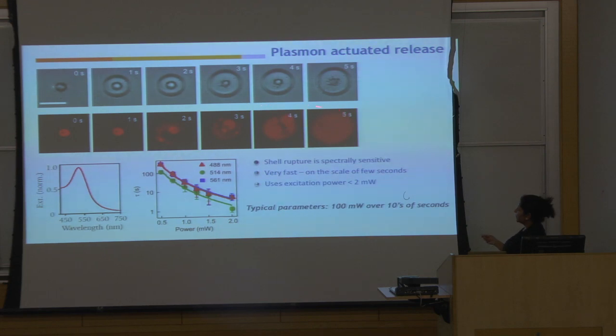These are frames of the same images. Here's the shell. Notice the shell is the one in the middle, not this circle. We'll come to what that circle is in a second. And here's the shell. In about 5 seconds or so, the shell breaks. The shell had dye inside, and the dye is released as it starts disintegrating here, and it breaks over here. Just some numbers. This is very fast compared to most other platforms that use encapsulation and release. This is on the order of a few seconds. Typically, people need very high power over tens of seconds, and the highest power we've used is about 2 milliwatts. So it happens very fast at very low power.